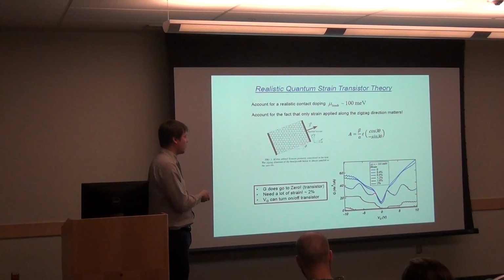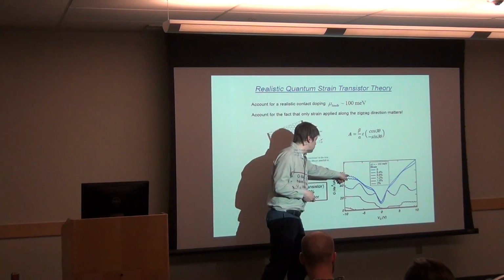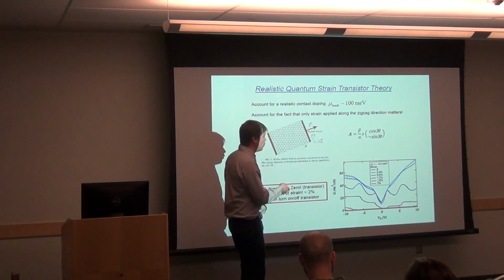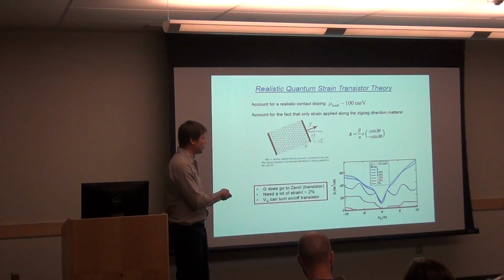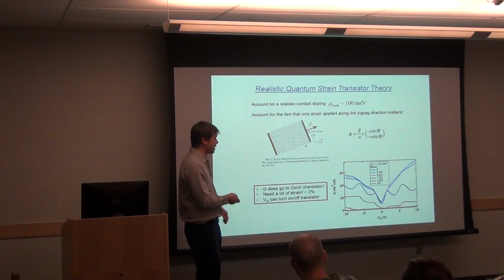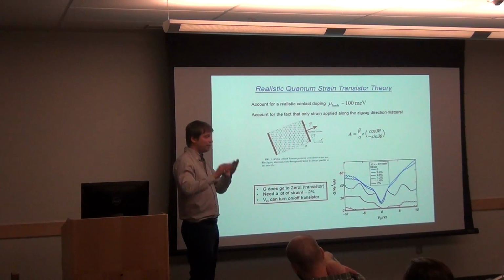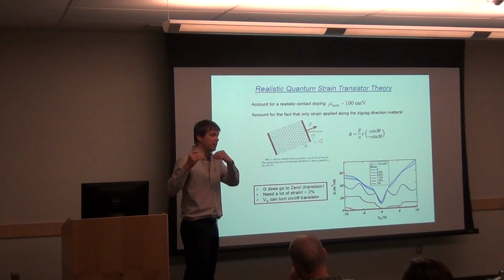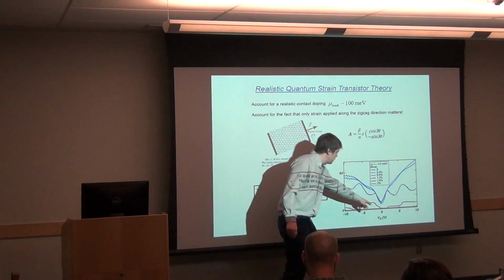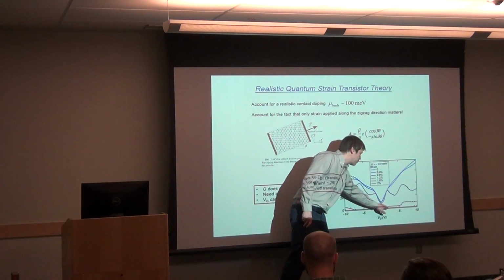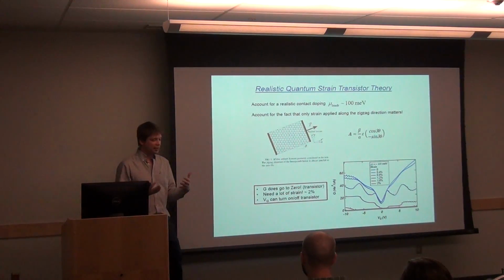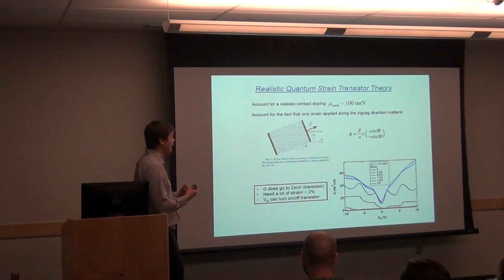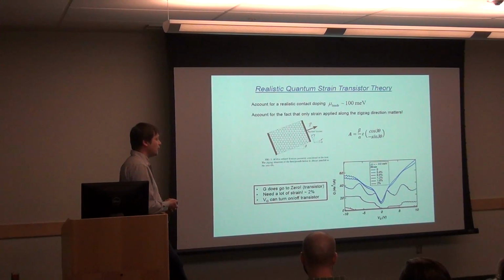So what is the outcome? This is our calculation for what happens with strain. If you start with the blue curve, that's unstrained, with 100 millielectron volt contact doping, like we have in an experiment, you get the following effect. If you apply something like 1.2% strain, you completely turn off the conductance. But what's especially exciting is that it's turned off only for some gate range. Meaning if I can create a system where I have this strain in the graphene, for example on a substrate, then I can just use the voltage to turn the graphene on and off. But it's pristine graphene, there's no defects in it. It's really a quantum mechanical reflection at the interface. And we built a quantum strain transistor.